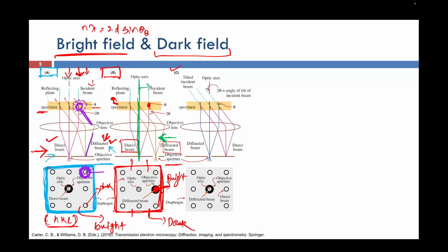Why? Because the aberration is a function of alpha, right? Alpha is the semi-convergence angle. In the last class we saw that. So these aberrations will start increasing. It will not be much, but still it will be significant enough for us to misinterpret the images and the information. So that is why we said, okay, the moment we are collecting all these beams away from the optic axis, the aberrations come. What we will do now is tilt the